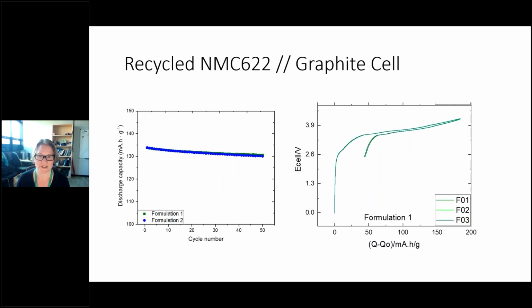And here we just show you, because we can, a full recycled cell in which we've remanufactured the NMC 622, and it's a recovered graphite. This is a little pouch cell that we made, which cycles actually pretty well for recycled materials, and very similar to what we would expect pristine materials to cycle as well.